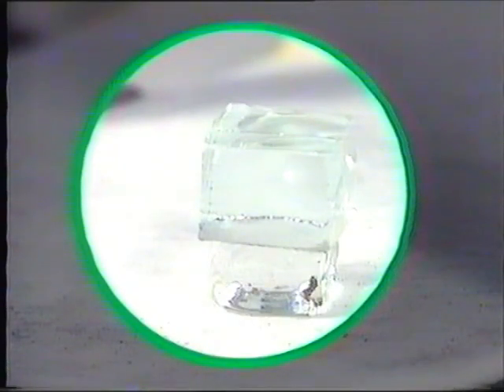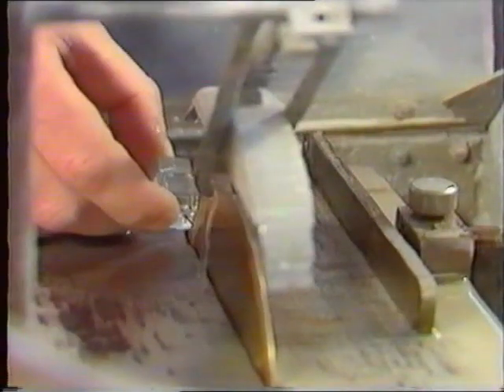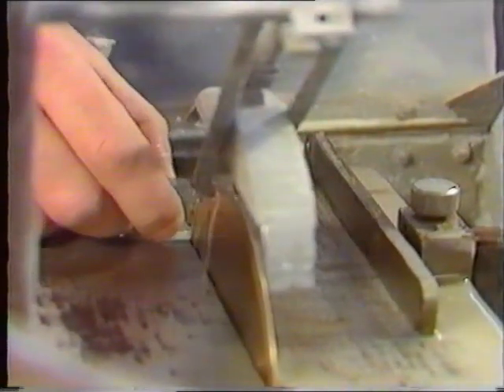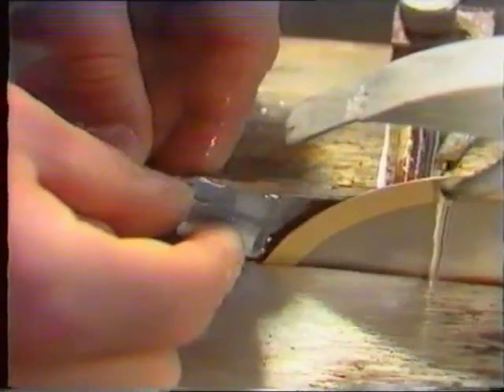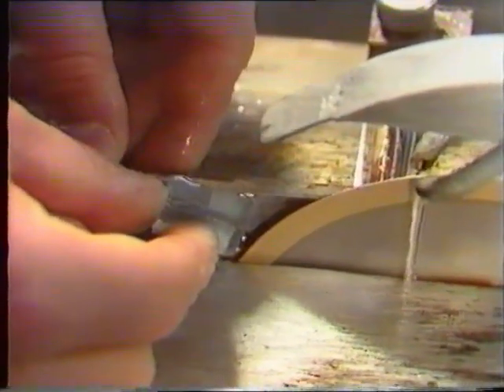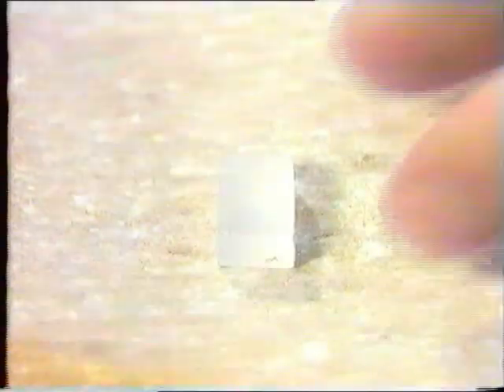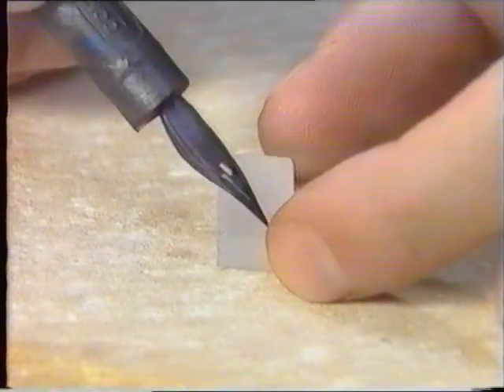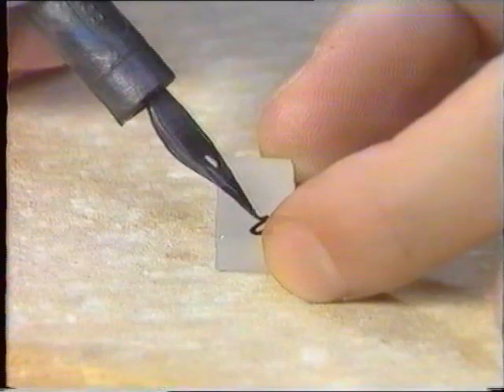From a correctly prepared seal, a 6 to 8 mm thick sample is cut. Top and bottom faces should run parallel and be perpendicular to the sealing face. The identification number is copied on the production glass.